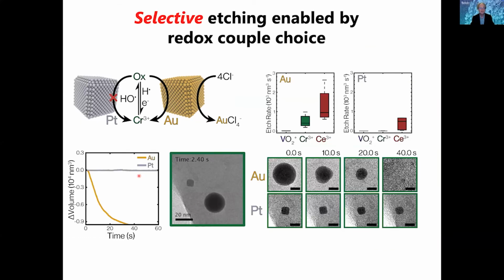Here's an additional line of evidence for this. We can have present simultaneously a gold particle and a platinum particle. And then we could put in different redox species. So it's the same environment chemically, and we can set the potential, depending on which redox species we put, such that the gold will be etched, but the platinum will not be at all. And vice versa. We can really move this around quite extensively.